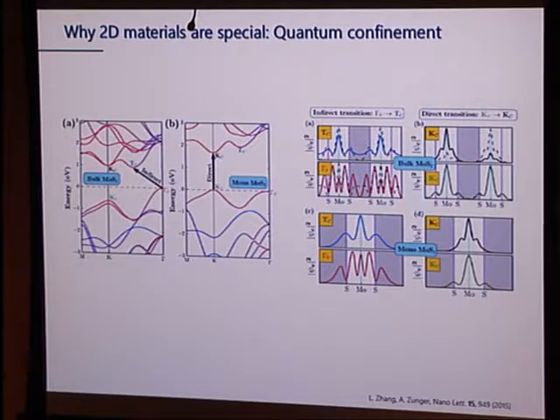And if you look at this as an indirect band gap semiconductor, right? So we have the valence band maximum at gamma, and then the conduction band minimum is somewhere inside the Brillouin zone. By the time you peel this down to a single layer, just one monolayer, something quite dramatic happens. It becomes a direct band gap semiconductor. So if you did photoluminescence measurements, it's dark as the night, and then suddenly this thing becomes actually quite fluorescent, quite strongly so, and particularly at low temperature is very strong and readily visible. It also absorbs like 2% of the light, a monolayer, right? So just to say that this is no mean feat.